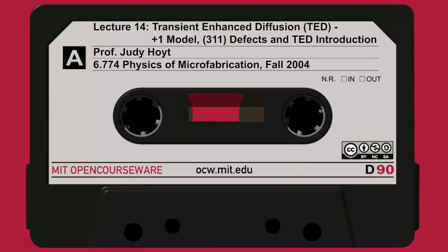How do we get that? Well, remember Fick's law. Flux is a diffusion coefficient times the concentration gradient. Here's a very crude way of estimating the concentration gradient. It's just the peak concentration divided by the distance over which it recombines, assuming they all recombine at the surface, or it recombines to zero. So here's a very quick estimate of the flux towards the surface, D_I Ci max over Rp. Now I need to know how much time it takes to dissolve all those.